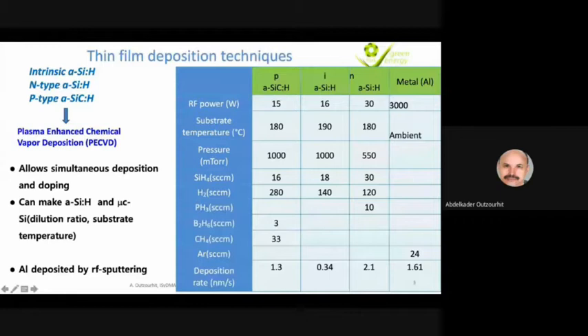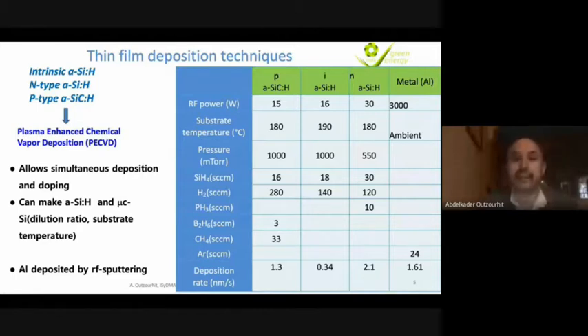For the P-type hydrogenated amorphous silicon carbide, we used a mixture of silane with a flow rate of about 16 standard cubic centimeters per minute, hydrogen with a flow rate of about 280 standard cubic centimeters per minute, in addition, of course, to methane to form the silicon carbide and diborane to P-type dope the films. For the intrinsic hydrogenated amorphous silicon, we used mainly a mixture of silane and hydrogen to form the film.